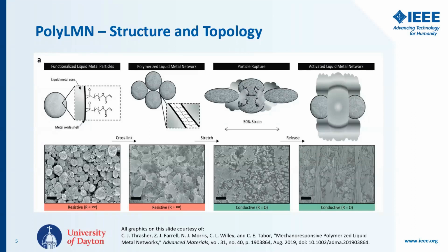Once the carrier fluid evaporates, the particles that are left behind are then cross-linked into a film. Strain is then applied to the nanoparticles, which ruptures the ligand shells, and the liquid metal spills out and is able to conduct electricity. This material can then be used to produce many types of soft electronics.